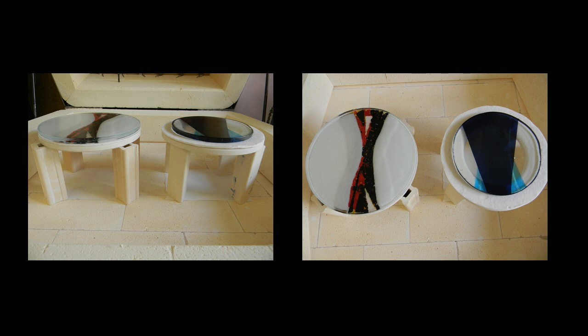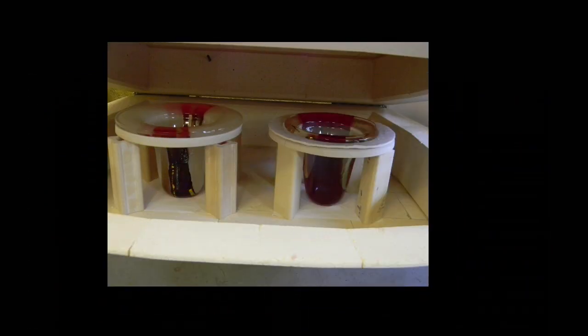In the right-hand image, on the right-hand piece of art, you can see that 1/8 inch fiber paper around the glass. Here you see the pieces after they've dropped through the mold. Now I placed a piece of thin fiber paper on the floor of the kiln so that when that glass went down and touched the base of the kiln, I was sure that I'm comfortable and confident that it would not stick to the bottom of my kiln.